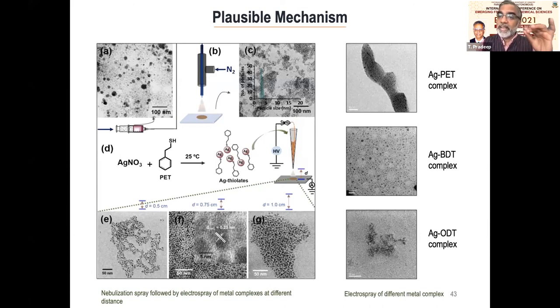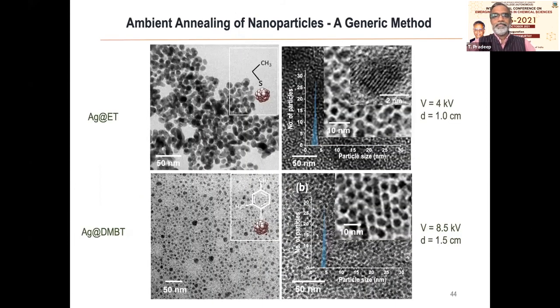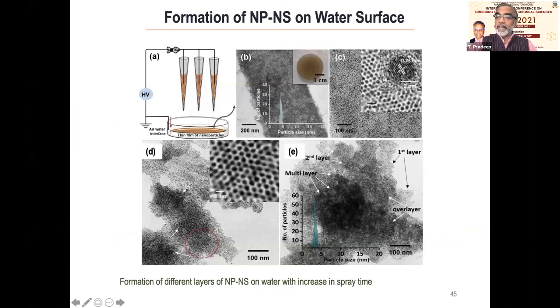You can take one particular monolayer, or you can have other monolayer-forming thiolates also, like ethane thiol or dimethyl benzene thiol. All of them also make these uniform particles starting from a polydispersed particle. It is a generic method. From such monodispersed particles, you can create thin films on surfaces. So these are freestanding thin films with highly uniform particles. They are not of regular order, however.